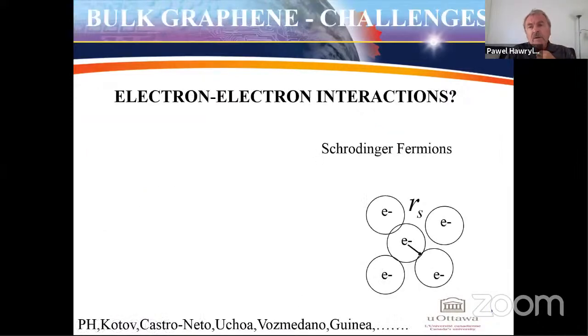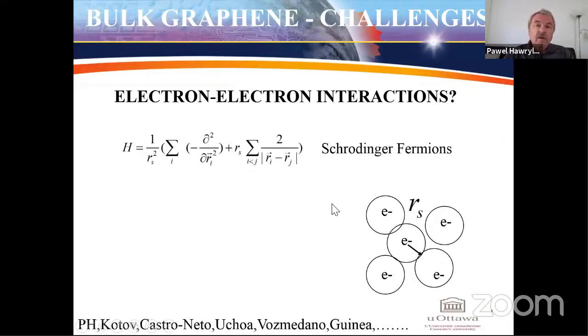There is a difficulty in addressing these materials, and that's related to electron-electron interactions. If you take Schrödinger fermions and you assign a little area per electron characterized by a radius of this circle Rs, then we can write the Hamiltonian for Schrödinger electrons, and it will have kinetic energy and it will have interaction energy, and the ratio of interaction to kinetic energy is proportional to Rs, to the distance. Yes? So at large Rs, Coulomb energy dominates. At small Rs, in a dense material, kinetic energy dominates. So we can tune the role of electron-electron interaction in materials by density.